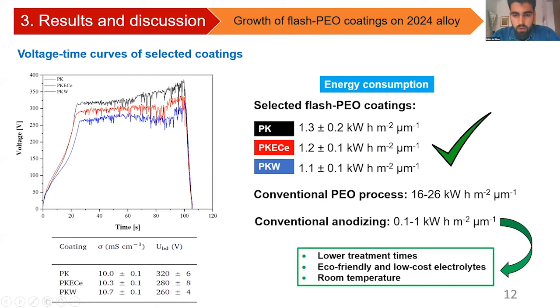And it's true that in comparison to conventional anodizing, we are at slightly higher values. But as a counterbalance, we use lower treatment times, we use an eco-friendly and low-cost electrolyte, and we perform the formation of these coatings at room temperature.